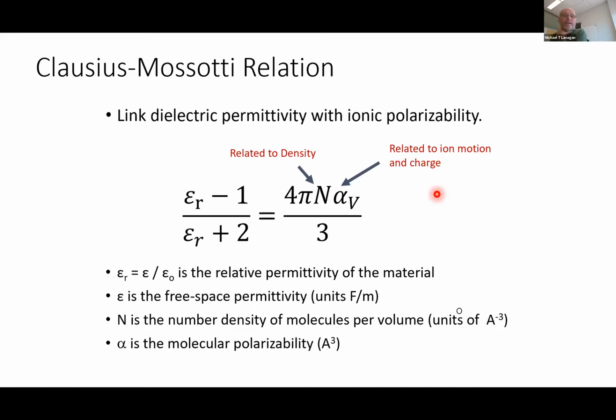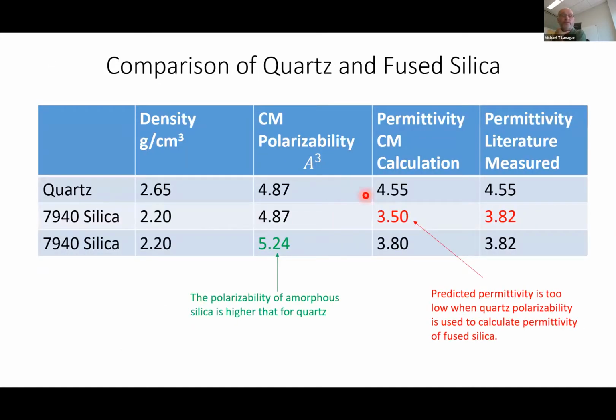So what we can do then is we can take that polarizability value from the table. We can measure the density and we can figure out how many atoms per volume we have. And from there, through this Clausius-Mossotti relation, we can get the permittivity prediction. So it's a pretty straightforward equation that relates the polarizability and the number of ions per volume. And that's a pretty straightforward calculation.